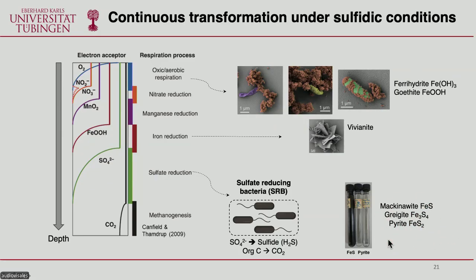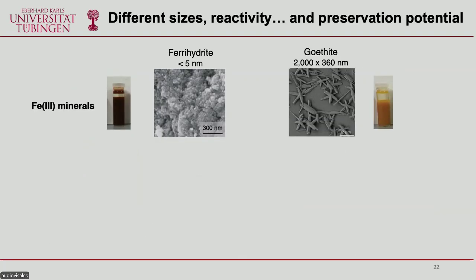You don't need to know all of them in detail, but the reason that I am bringing them up here is because the names indicate different identities, and that indicates different sizes, reactivity, and also their preservation potential. Essentially, when you have something small, like ferrihydrite, these are less stable in the environment. They can transform over time to something like goethite, which has a larger crystal, more crystallinity and a larger structure. And so they can be preserved much longer on geological timescales.